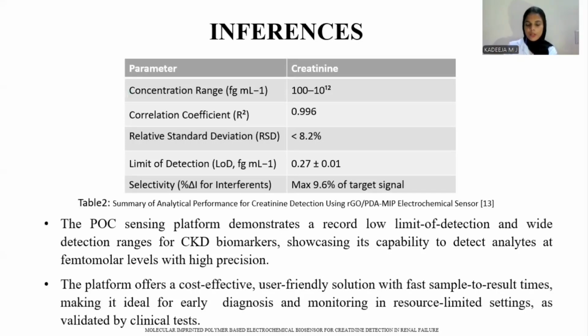This table represents the summary of the analytical performance of creatinine detection using the proposed RGO-PDA MIP electrochemical sensor. In that method, we get a concentration range of 100 to 10 raised to 12 and a correlation coefficient of 0.996, a relative standard deviation of less than 8.2 percent, a very low limit of detection, and selectivity of maximum 9.6 percent of target signal.